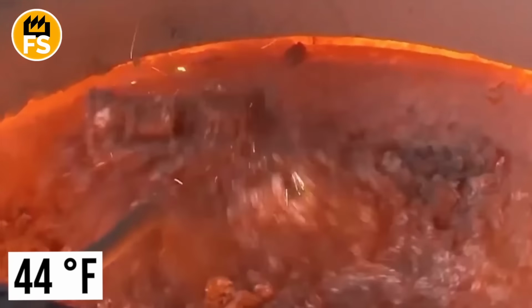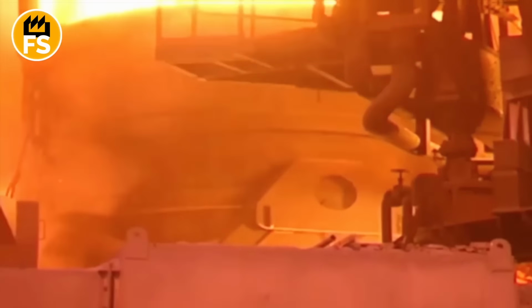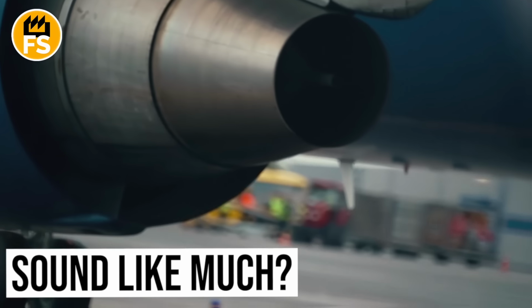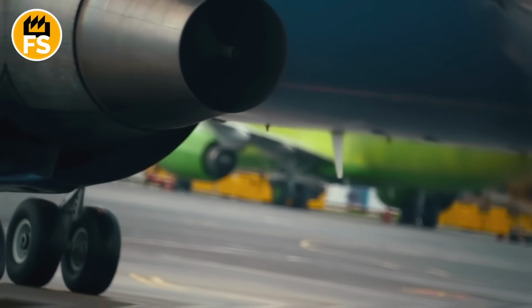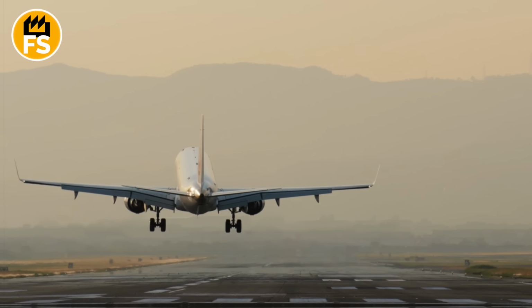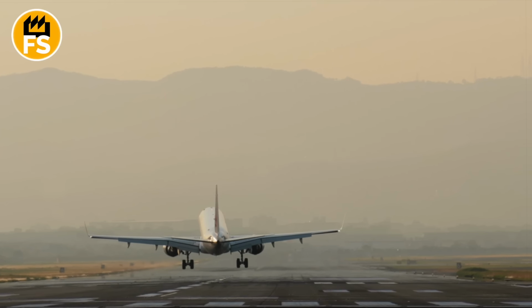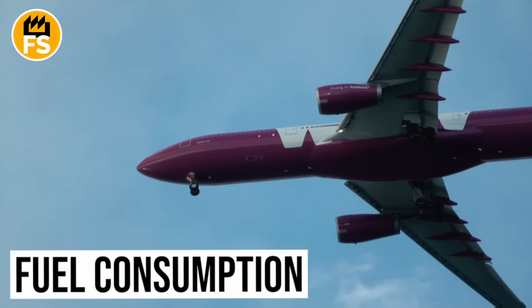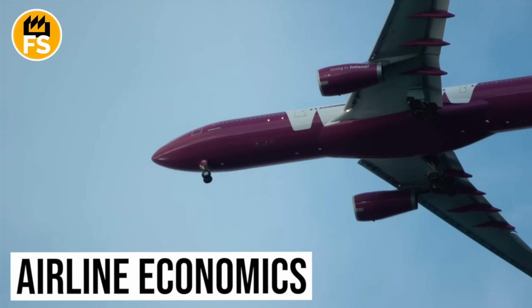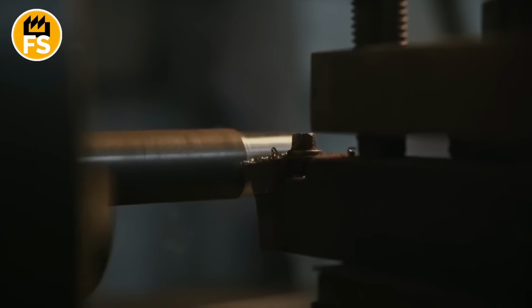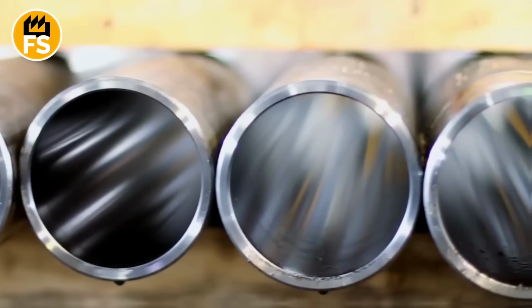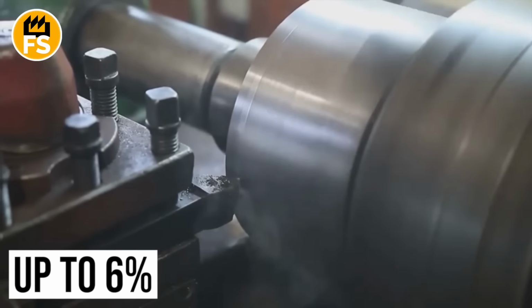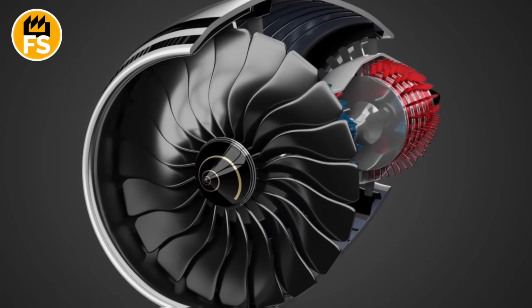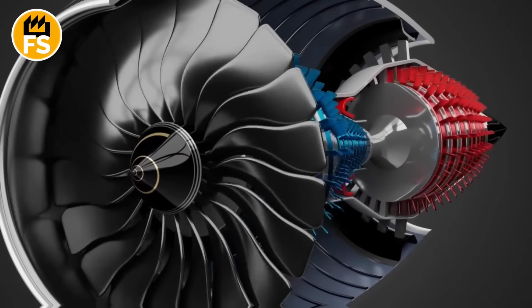Adding just 3% rhenium to a nickel superalloy increases the operating temperature by about 54 degrees Fahrenheit. Doesn't sound like much, but in jet engines, every 18 degrees of additional temperature gives roughly 1% increase in efficiency. And efficiency means fuel consumption, flight range, airline economics. Modern superalloys contain up to 6% rhenium. These are the so-called second and third generation superalloys.